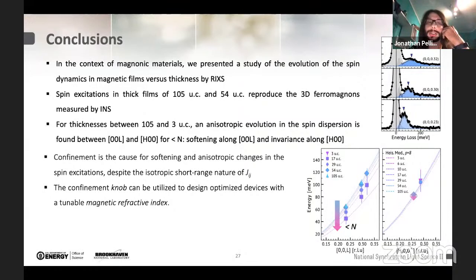We observed for the first time ferromagnetic excitations in bulk-like films that were 105 and 54 unit cells thick, and we were able to reproduce the three-dimensional ferromagnetic excitations that were measured by inelastic neutron scattering, which makes RIXS a reliable technique to perform this kind of investigation, because RIXS is a pretty novel technique and it requires a strong comparison with more mature techniques such as neutron scattering.